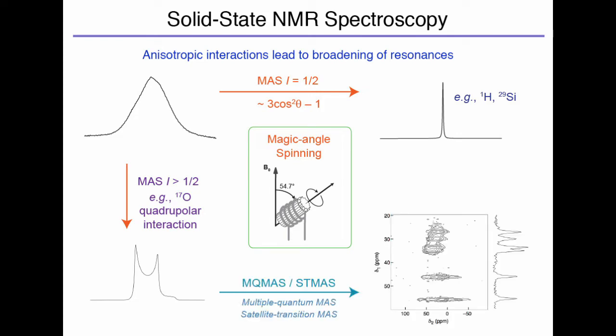So in such cases, what we need to do is then apply two-dimensional techniques, such as multiple quantum magic angle spinning or satellite transition magic angle spinning. Now, I'm not going to go into that, but we essentially get these plots here that can be read exactly like a contour map, as if you were going hiking in the Lake District. So the closer the contours are together, they indicate a peak. And what you're looking for is the peaks you have in your spectrum. So if you just counted up the number of ridges that correspond to each peak, you would see that you've got six peaks here, so six environments. It's as simple as that as how we're going to interpret it.